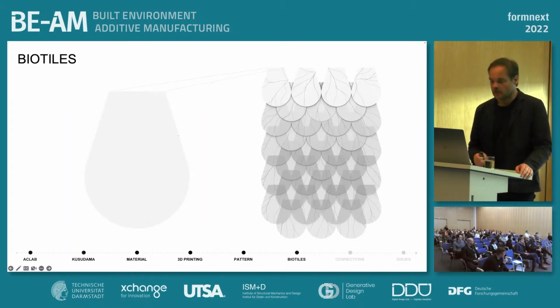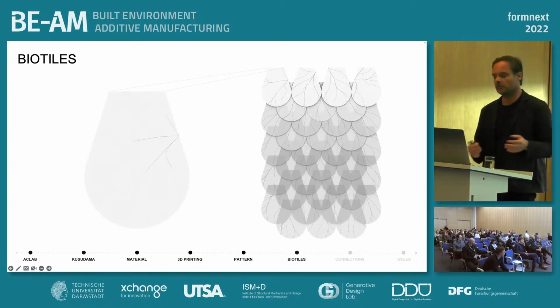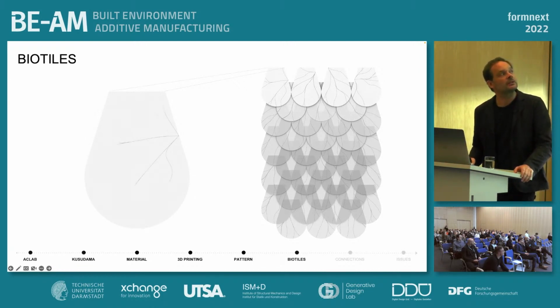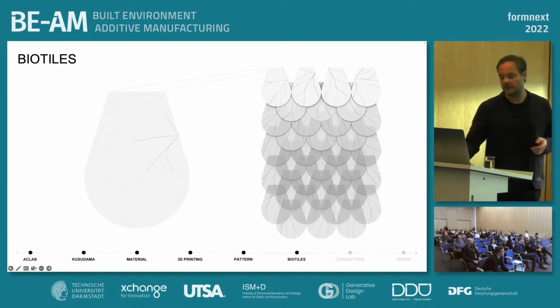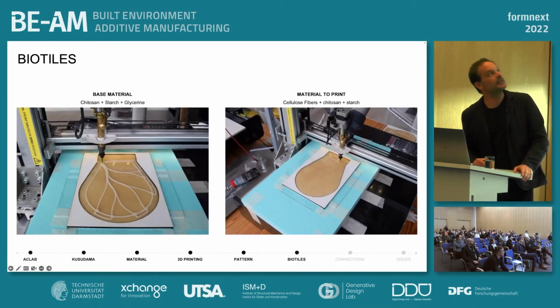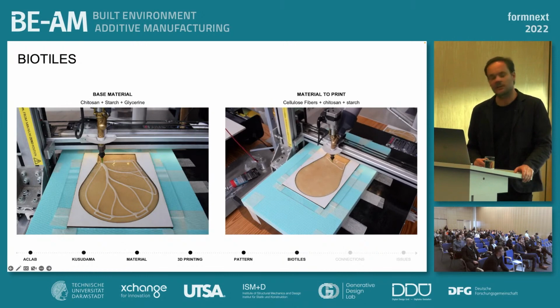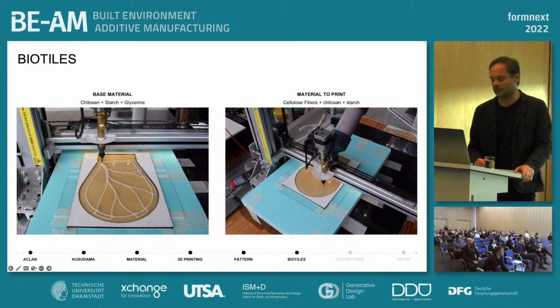So to achieve the overall shape would be really easy by defining specific molds and pouring the liquid material, and then we were reinforcing the membrane with this structure. We thought also, crossing here the inspiration of the veins of plant leaves, with the aim of acting as a structural reinforcement. The prototype was supposed to have 35 tiles with different shades and textures, and we started producing these. We made previous testings in July that worked pretty well, and this image is from October when we started the final prototype.